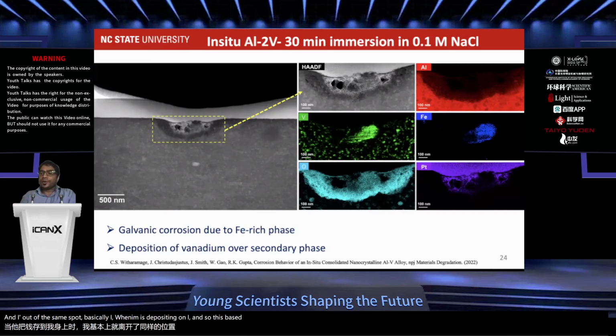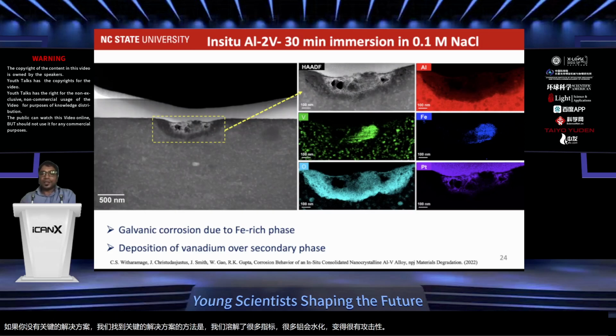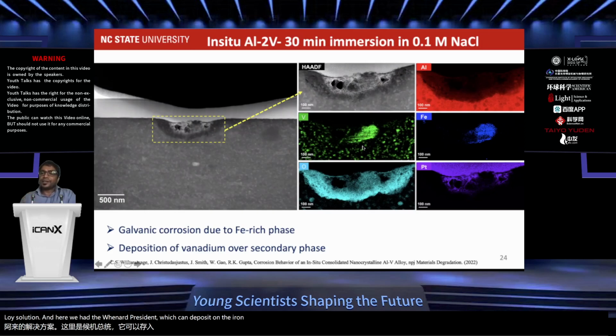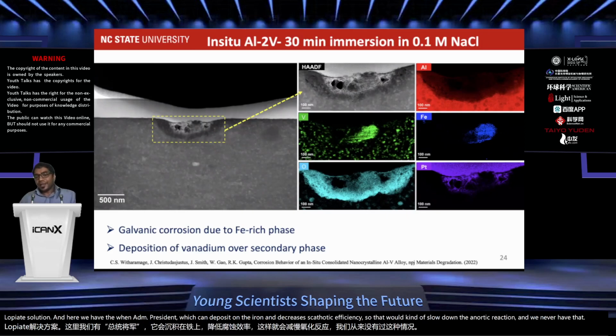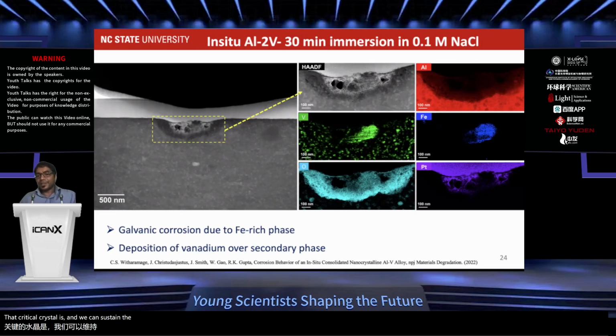So based on that, we put our hypothesis that, in case of the pitting corrosion, I mean, the pit growth or repassivation, there are 2 competing mechanisms, right? So a pit can repassivate if you don't have the critical pit solution. And the way we form the critical pit solution is that we dissolve a lot of matrix, a lot of aluminum that hydrolyzes and forms a really aggressive low pH solution. And here we have the vanadium present, which can deposit on the iron and decreases cathodic efficiency. So that would slow down the anodic reaction, and we never have that critical pit solution. We cannot sustain the critical pit solution and it repassivates.